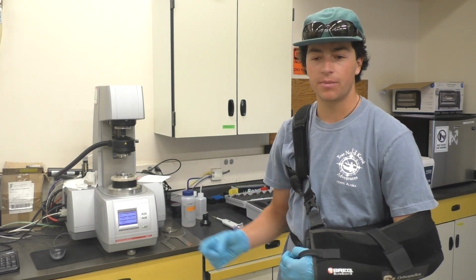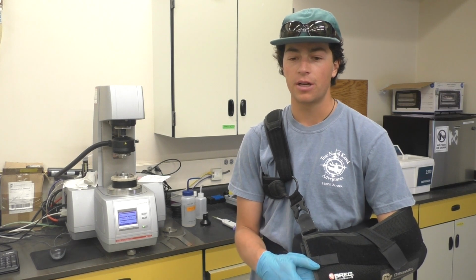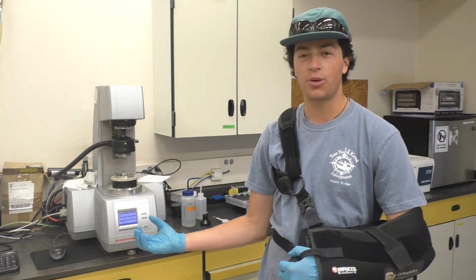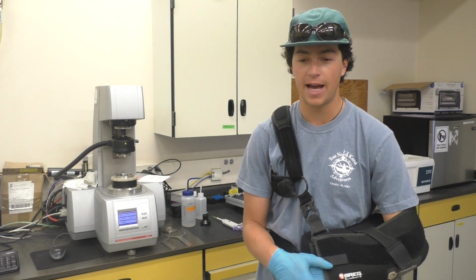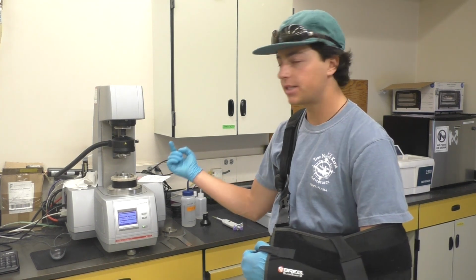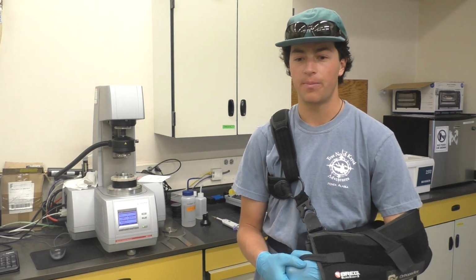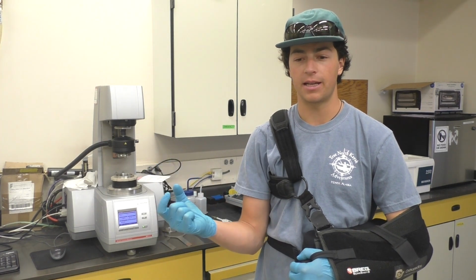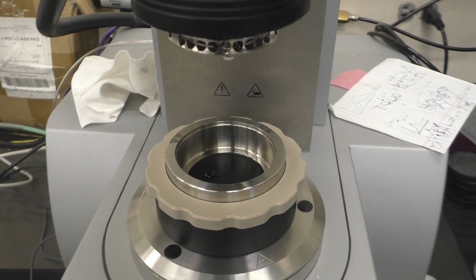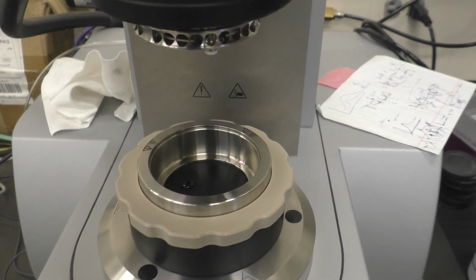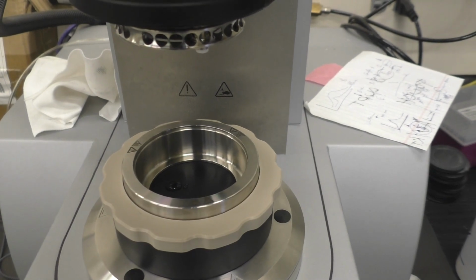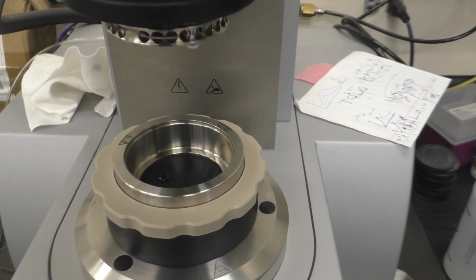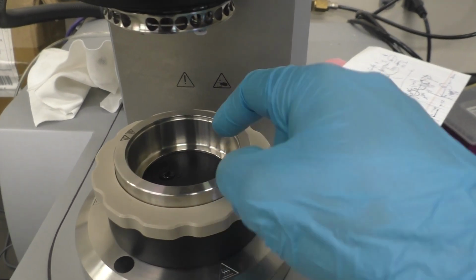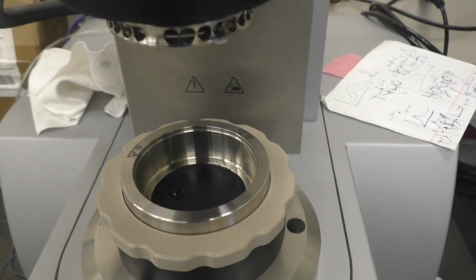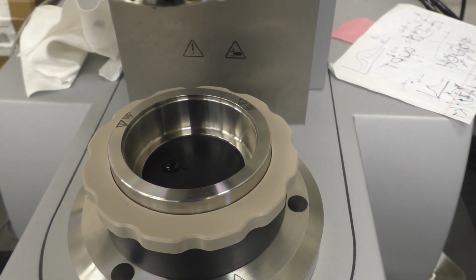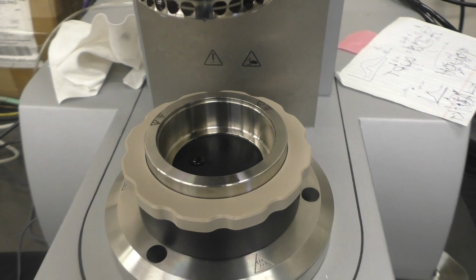This measuring system consists of two parts: a stationary base plate to which the disc of ski base material is attached, as well as a rotating measuring system unit that involves the disc and the pins. To test a ski base sample, we first load a disc of ultra-high molecular weight polyethylene ski base material into the base plate, which you can see here. We then add about 200 microliters of water to help simulate the snow surface.